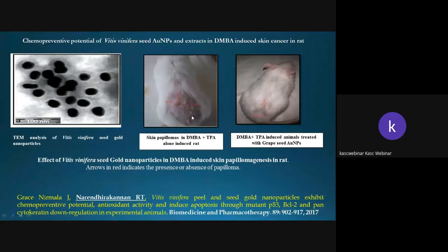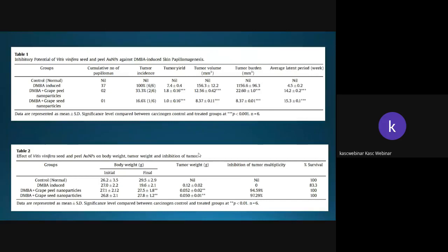And here you can see the rat skin papillomas in DMBA and TPA induced rats, treated with the grape seeds. The topical application of these gold nanoparticles during the initial stage of DMBA and the promotional stage of TPA induced skin papillomagenesis significantly reduced the tumor burden. The development of tumors commenced at 4.5 weeks and was evident in the carcinogen-treated groups by the end of the 8th week. The gold nanoparticle treated group exhibited delayed onset of tumors, at 14.2 and 15.3 weeks. So topical application of 50 nanometer Vitis vinifera peel and seed gold nanoparticles delayed tumor formation. We administered the gold nanoparticles earlier and then provided the carcinogen, so this will delay the formation of cancers.